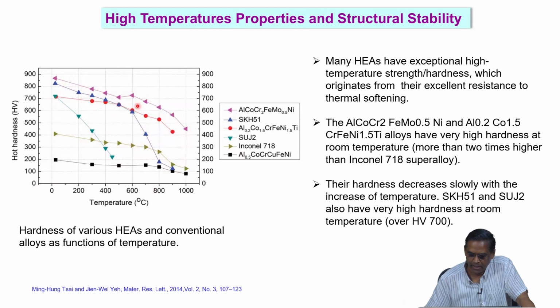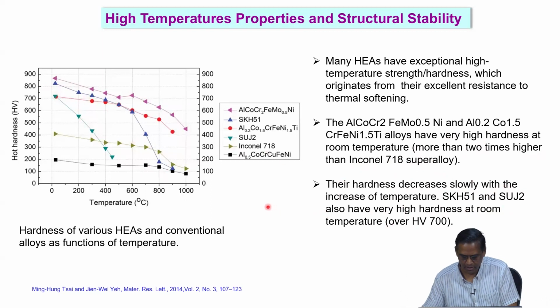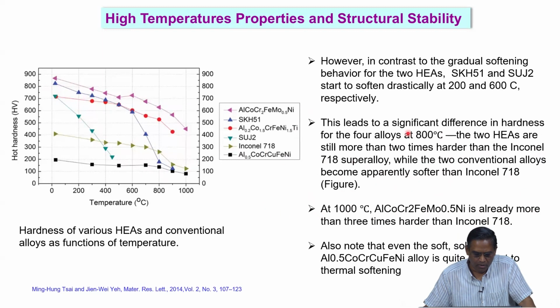Okay. So all these high entropy alloys have very high hardness at room temperature, more than 2 times higher than Inconel 718 superalloy, and their hardness decreases slowly with increase of temperature, but the conventional alloys have a very high hardness at room temperature, but it changes drastically with increasing temperature. This is another important point. So what is the advantage?